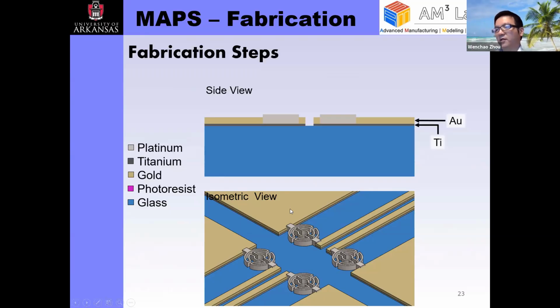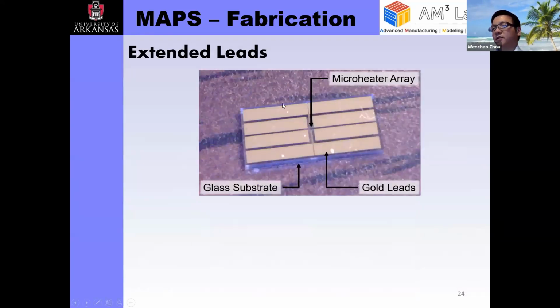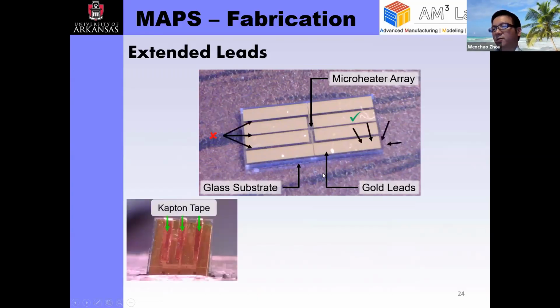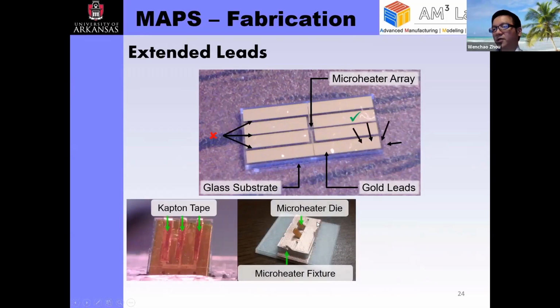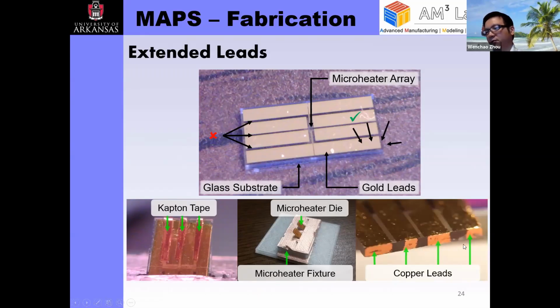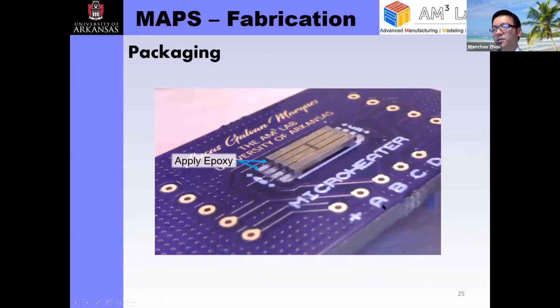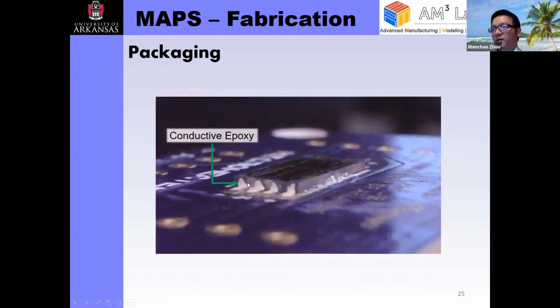Don't be concerned that this might be very expensive, because it's not. We're talking about a couple of 100 nanometers thick of these materials, so they're using a very, very small amount of platinum and gold. And so this is the die of the microheater that we just made, with 4 microheaters in the center. This is a glass substrate. Then in order to package it, we deposit additional copper leads on this side so that it can be connected to the external package. So this is a PCB board that we designed to put a microheater die on, so that we can apply some conductive epoxy to connect to these microheaters.